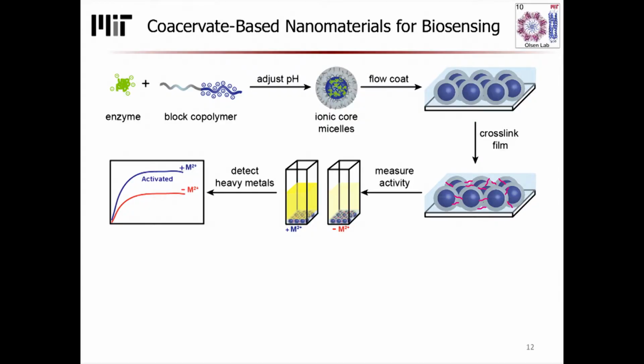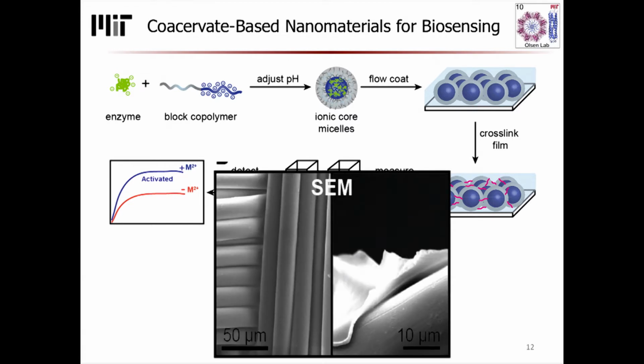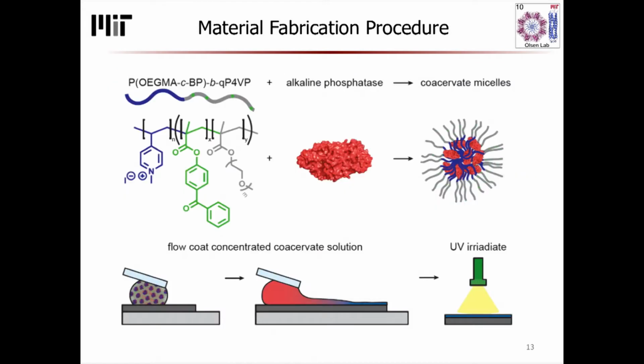In particular, we're trying to use this technology to produce sensors for heavy metal contamination in water. This is a very interesting technology to us. As I show here in an SEM, you can very simply dip coat or flow coat these materials to produce, for example, fabric coatings or integrated sensors in textiles. The way we developed the particular example sensor I want to show you today is using this copolymer of polyvinyl pyridine with oligoethylene glycol methacrylate.